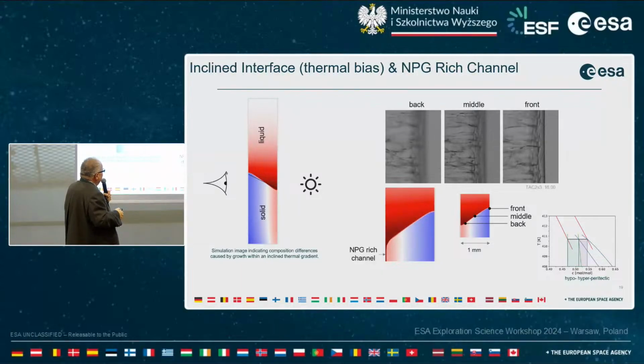And since we have here 4 clamps, 2 hot and 2 cold, they are not working absolutely perfectly. There's a small deviation in temperature, which is normal. We get a small decline of the solid-liquid interface. And this leads, for example, to an NPG-rich channel.